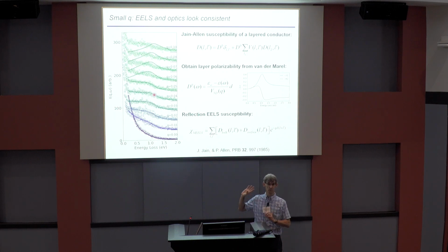This is somewhat technical, and I don't want to put everyone to sleep because it's already after 3 o'clock. But what this means is that we see a plasmon at small momentum. And we see it at the same frequency with the same width as they see in optics. So while EELS and optics measure slightly different quantities, the two are consistent with one another as far as we can tell using just basic electromagnetism. Okay, so there's no reason to suspect the experiment at this point.